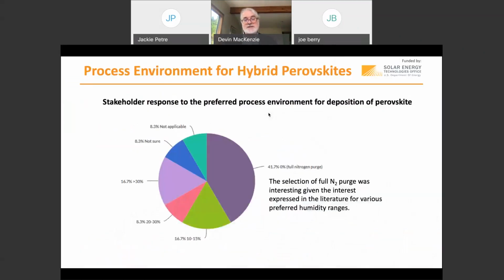These are confidential names, so I'm not going to reveal who they are, but the stakeholder respondents represent a significant fraction of US MAP participants in all the perovskite companies in the US, almost all of them. The interesting thing, thinking about basic stuff we know is important for the process environment, was that the big choice was full nitrogen purge. I thought that was interesting because in the literature people talk about a Goldilocks situation: too much, too little, just right, and they wanted these magic windows. But the field actually wants just a full nitrogen purge environment, and that informs how you would construct an enclosure for roll-to-roll or sheet-based processing.